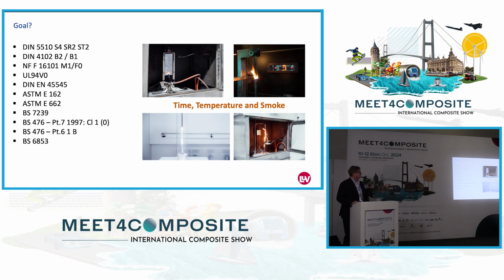But you have also standards for building and construction. You have the UL 94 test, which is also an orienting test. It's very simple, and if you fail with UL 94, in most cases it doesn't make sense to go on with this formulation. So that's where we can help. We can do these tests in our laboratories. When you do these tests, you have different characteristics you have to achieve: time of fire, dripping of material into wool or something like that, and so on and so forth. So that is the first thing you have to talk about: what is the standard you would like to achieve?